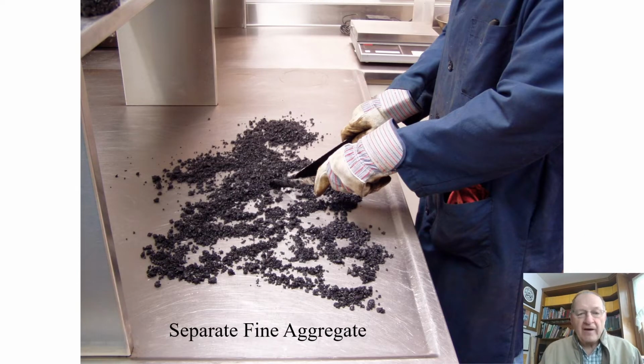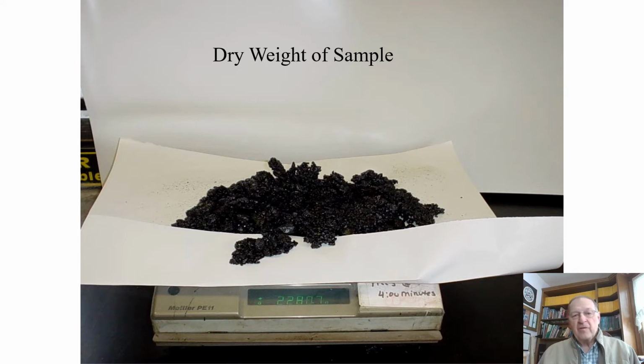So here's a photograph of separating the fine aggregate. There could be aggregate particles that are larger than 1/4 of an inch, but the key is the sand-sized particles, to break them apart enough that there is no trapped air inside them. Then we take a dry weight of the sample. Here you can see it sitting on paper on top of the scale.